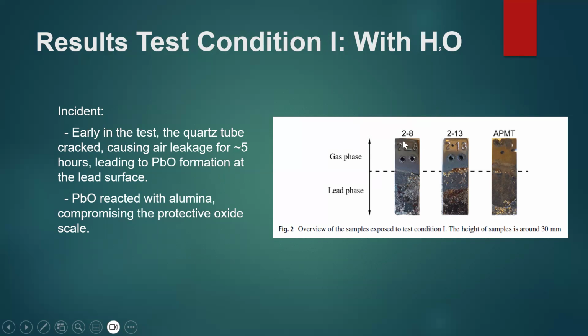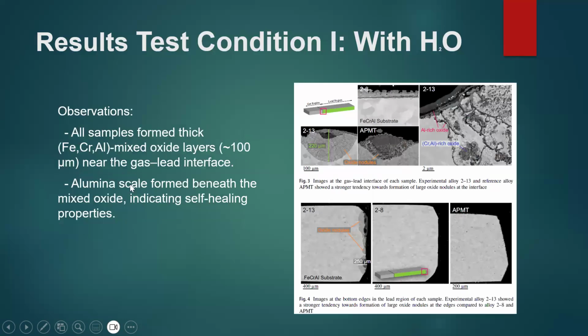This sample covers alloy 2-8 and 2-13, and this is APMT. With observation we can see a thick iron-chromium-aluminum mixed oxide layer around 100 micrometers near the gas-lead interface, and an alumina scale formed beneath the mixed oxide, indicating self-healing properties.